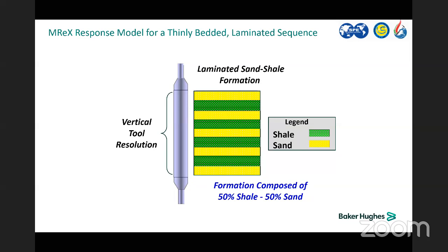Permeability in turbidites, usually the thin lamination in the deep basin, the permeability of the sand is high, but due to the resolution, you are getting an average between the shale and the sand, so the permeability from the logs is low. Here we are reconstructing. We applied a similar technique of extracting the laminar shale volume from the NMR, and you will see that based on this model, you can get the actual porosity and permeability from NMR after excluding the laminar shale.